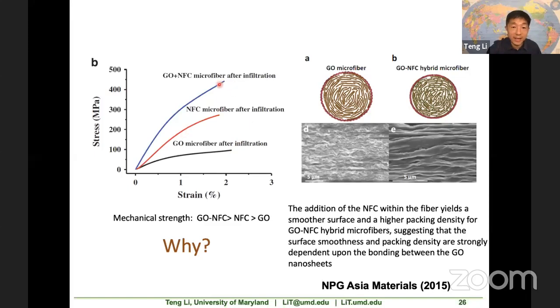However, when we hybridize the graphene oxide with NFC, we found that this composite fiber is both stronger and also tougher because it dissipated more energy to fracture it. To understand why, I'll explain in two slides. First, why this hybridized microfiber is better than just the pure graphene oxide. Then I'll explain why this one is better than the pure NFC one.